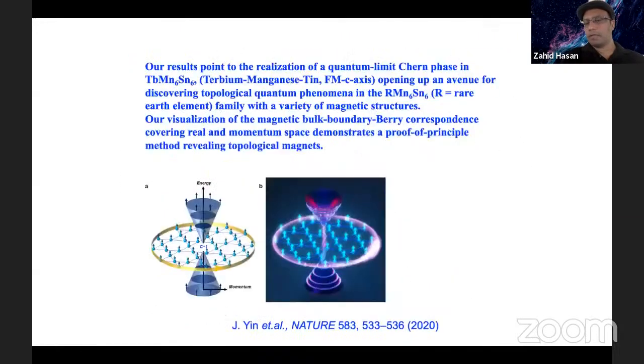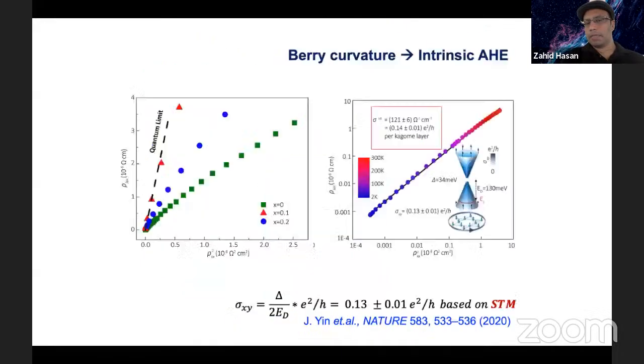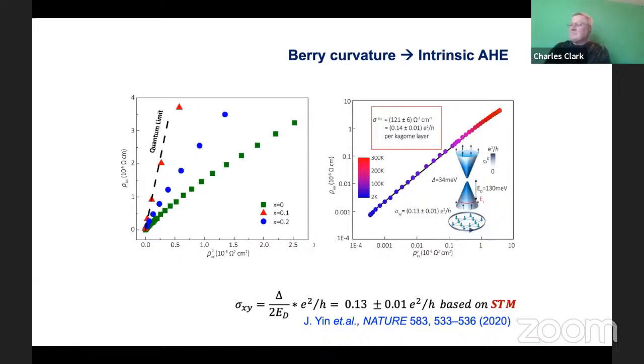This is what I was thinking about. I meant to be saying that the gap is so large that if you take these magnets and have two domains adjacent to each other, then at the interface there will be a dissipationless current at room temperature in principle. And this inelastic scattering, at least it would be near dissipationless. So this is our hope, our current hope when we don't have a room temperature superconductor.